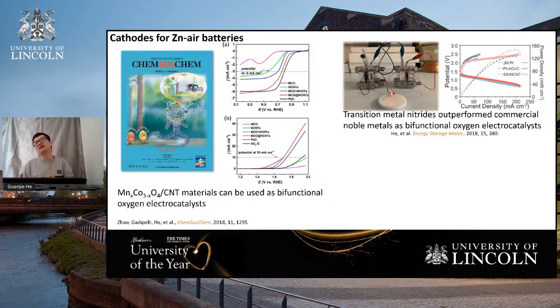I developed another series of the transition metal nitride materials. And those materials can outperform the commercial noble metals as a bifunctional oxygen electrocatalyst. And these metal nitride materials are much cheaper compared to the Pt or IrO2 as well.